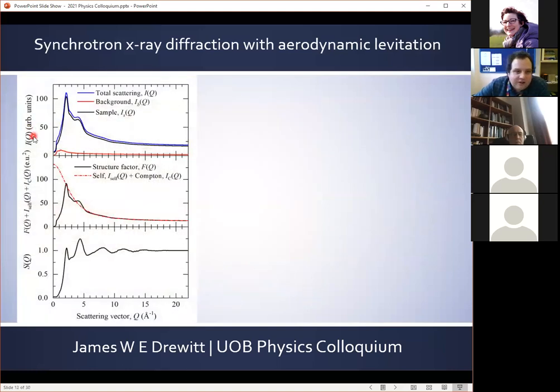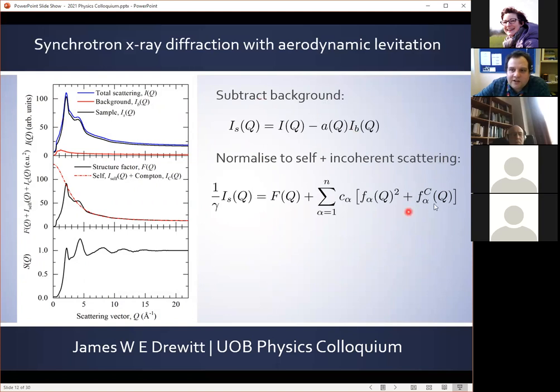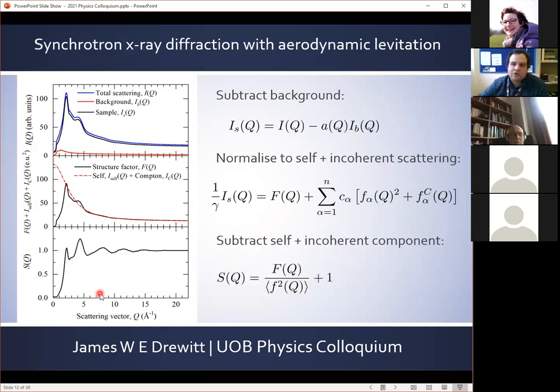Very briefly, I'll just go over the data reduction for a synchrotron X-ray diffraction experiment for a levitated liquid sample. You can see here in blue we have the total scattering, and then our background scattering in red, which is really quite small. Since it's a containerless technique, most of the scattering is coming from the liquid sample, and our background mostly comes from air scattering. So we subtract this background and normalize it to the self and incoherent scattering, the Compton scattering, which we then subtract in order to obtain our total structure factor, which contains the coherent structural information of the liquid.